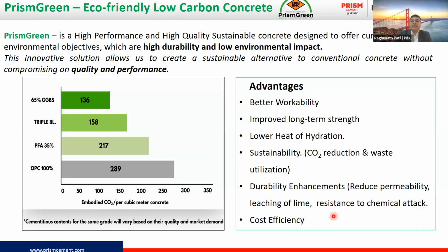And durability enhancement, so reduced permeability and leaching of lime. When we add pozzolanic material, it consumes the calcium hydroxide in concrete, and hence makes additional CSH gel, which gives the concrete higher strength, and also fills the voids inside the concrete, and reduces the permeability. It also helps against leaching of lime, and it is very helpful for resistance to chemical attacks. And if you compare the cost, this pozzolanic material is cheaper than cement, so it is a cost effective solution.